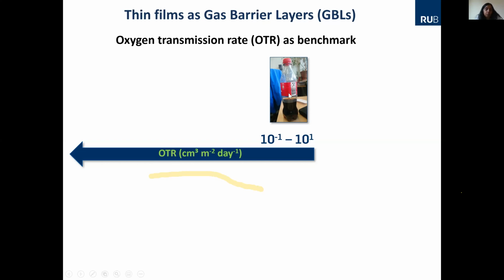So for a Coke bottle, of course, it's a degradable product, our Coke inside. It can also degrade over a period of time. On the other hand, we have to make sure that no oxygen or water gets transmitted inside or seeps through and degrades the Coke inside. So normally you have plastic PET and then a very thin layer of SiO2 coated on it, to prevent the diffusion of gases from outside. This value, 10 to the power minus 1 to 10 to the power 1, is not high end.